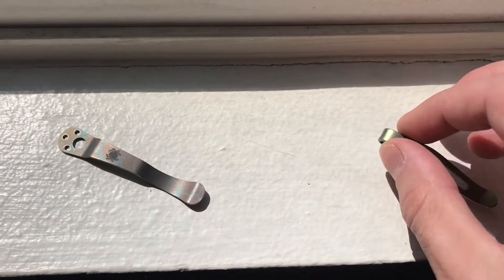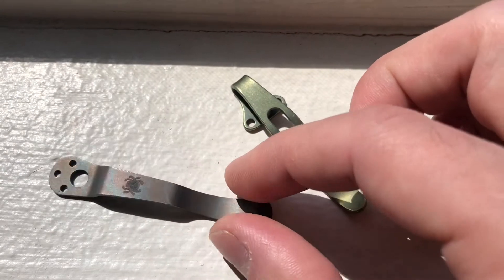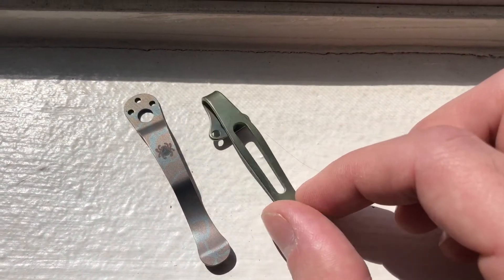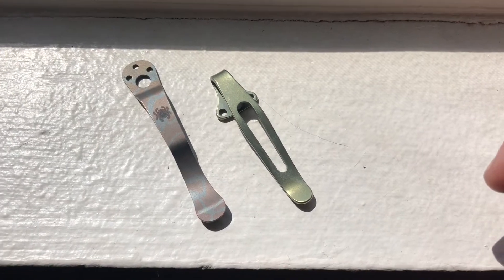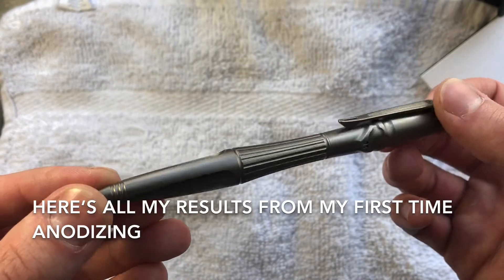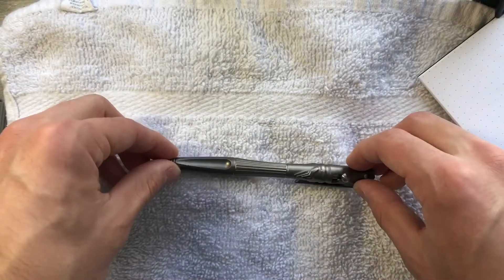Let's take a look at the other one. You can see that light gold color, a little bit greenish. I think most of the issues I'm experiencing are just from the batteries. I used the same eight batteries for like five different pieces that I anodized already, so I think it's just a matter of having a more powerful power supply. Really cool result, and that rubber cement definitely works. This is our sort of baseline titanium color - here's a pen from Reikknife. I do have a couple of videos featuring this pen, so hopefully you have a good sense of what it looks like normally. It's just sort of a gunmetal silver kind of color.